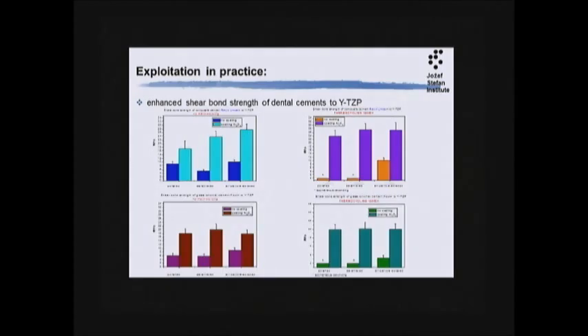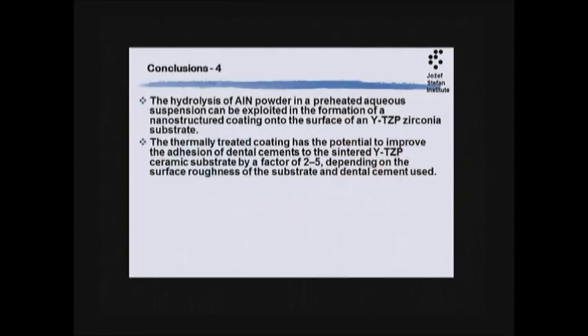So there is an alternative, but according to Matthias, it's not necessary, because that's another operation. You can deposit the layer very quickly, but then you need another heat treatment, and that takes perhaps 3 to 10 hours. Excuse me. And if this is not necessary, why bother? But if there is a problem with sandblasting or somewhere else, that might be a solution. That's one of the possible solutions, I will say.